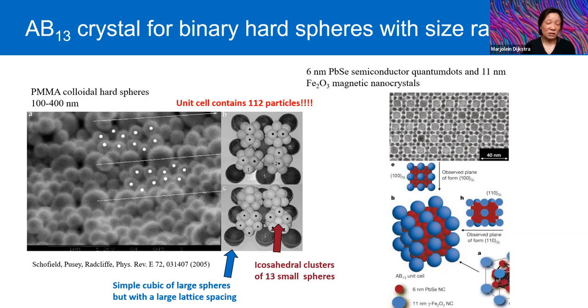But in this case, it forms a simple cubic lattice, but with an extremely large lattice spacing in such a way that icosahedral clusters of 13 small spheres fit in the center of the simple cubic unit cell. And moreover, these icosahedral clusters are rotated by 90 degrees with respect to their neighboring icosahedral clusters. And these icosahedral clusters are made of 13 small spheres. So somehow the system, if you mix big spheres and small spheres together, knows that the small spheres have to make these icosahedral clusters, and then the big spheres are organized around this.